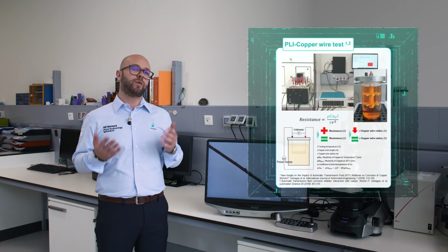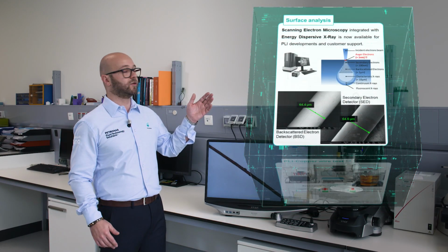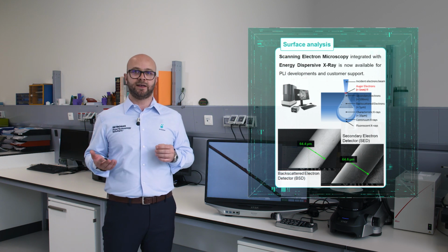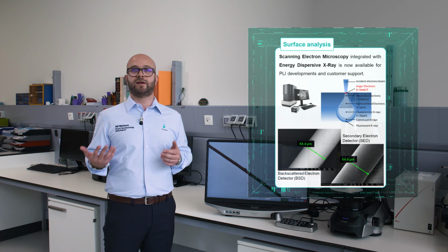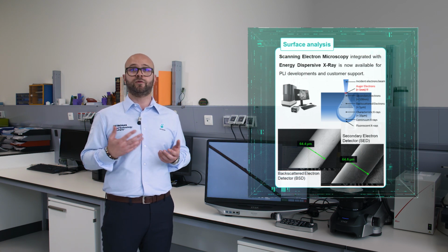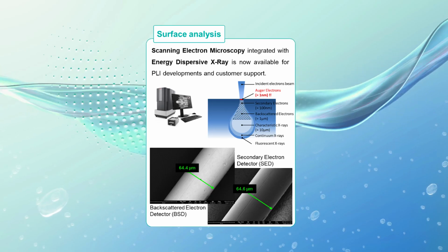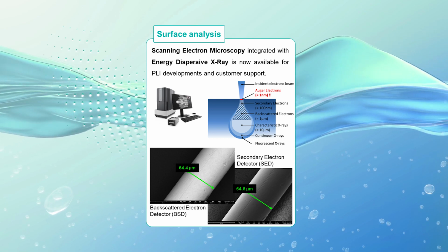On top of this, we decided to introduce the scanning electron microscopy coupled with EDX in order to analyze the surface of the wire after the test, in order to get also information regarding the corrosion mechanism that lead to the failure of the test.